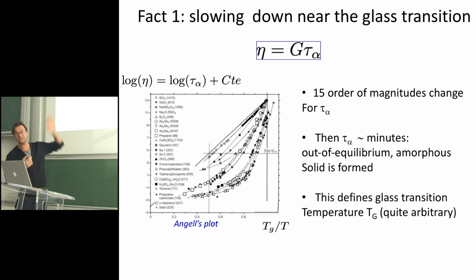And experimentally, you can access this quantity by measuring the viscosity of the liquid. The viscosity is essentially G, which is a high-frequency modulus, times this time scale. And in experiment, you can measure this time scale by measuring this viscosity over many decades. If it's very hot, the frequency is terahertz, so 10 minus 12 seconds, until a scale of minutes. So you have more than 15 decades where you can study the dynamics. This axis would be the log of the time as a function of inverse temperature. So when you cool the system, the dynamics slows down a lot.